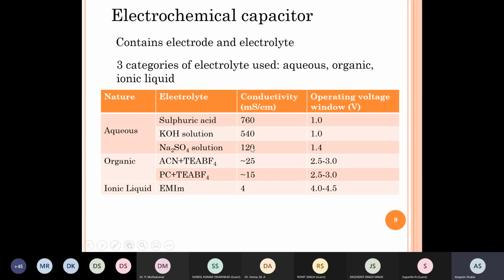And sodium sulfate solution has much lower conductivity compared to the other two, but it brings an advantage in operating window. The operating window, which is the maximum voltage to which the capacitor can be charged, is around 1 volt for the first two aqueous electrolytes, while it is 1.4 volt for sodium sulfate solution because it suppresses the breakdown of water. Remember that if these solutions are based on water as solvent, then water starts to split if the voltage at the electrode increases beyond 1.25. That is somehow suppressed by sodium sulfate, so it can increase the voltage window. Therefore, people also use sodium sulfate solution in spite of its lower conductivity.